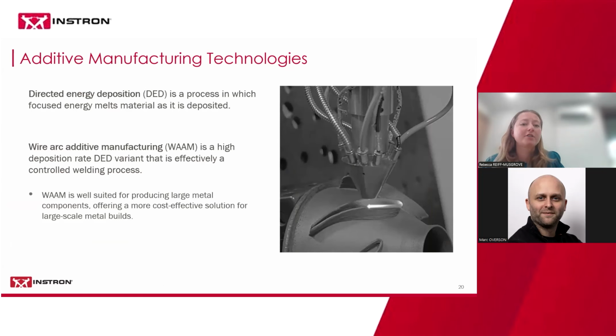And then the final one I'll touch on, because we do see it as well, is directed energy deposition, or DED. This is a process where you melt the material using a focused energy source as it's deposited. The easiest one to wrap your head around is often wire arc additive manufacturing. You can think of it as effectively a controlled welding process, where you use that weld to keep building up a 3D part. This is a really high deposition rate variant, so it's very suited for producing larger metal components, as it's often more cost effective than the powder bed fusion methods for large scale builds. So those are the three that I see the most often.